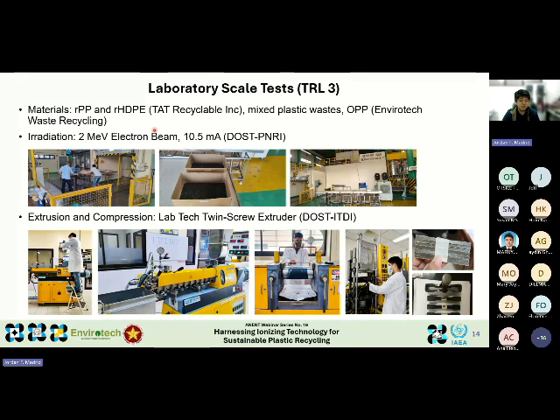So the recycled plastics were then irradiated at PNRI using a 2 mega electron volt electron beam. After irradiation, the samples were blended, extruded, and compressed into specimen form suitable for mechanical testing. We then conducted a series of evaluations to study their characteristics, focusing on mechanical, thermal, and other physical properties. The results of these experiments, which I will show you next, provide very promising insights into how radiation can truly add value to recycled plastics.